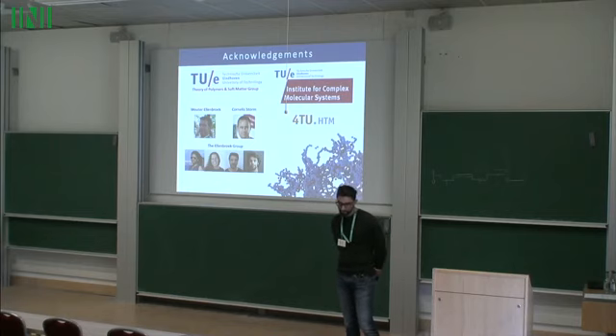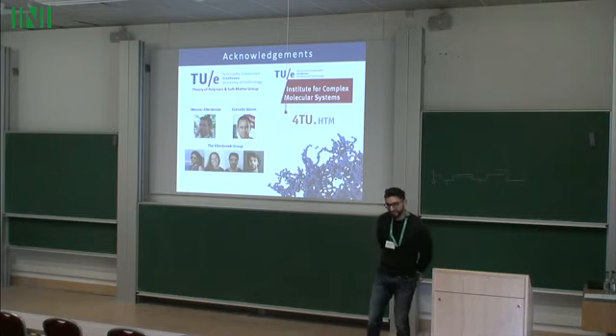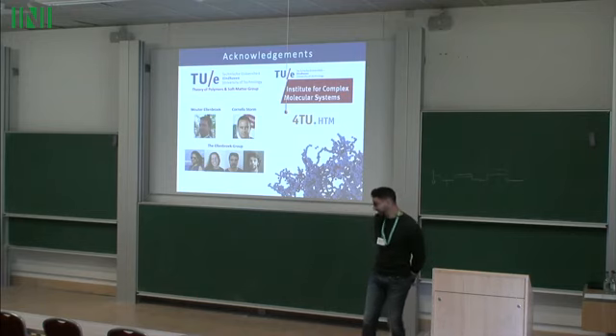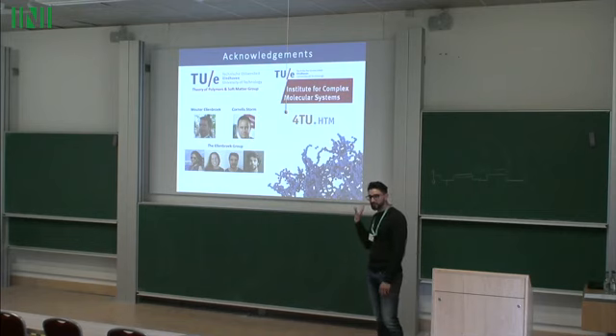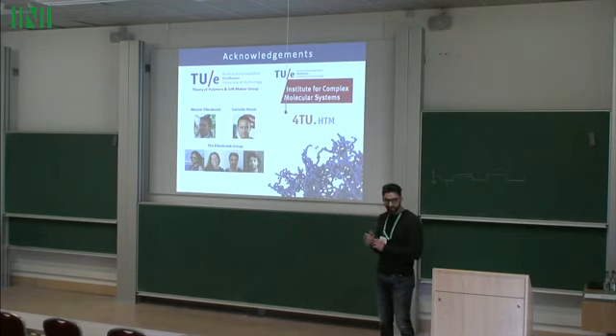What about all these composite systems that experimentalists make, which are more complicated? Can you add on to this? Yeah, I think so. This argument works really well when you have a dilute polymer network. If it's more concentrated, then it becomes difficult because you have entanglements that might govern things, and that will complicate the entropy, because now the entropy is a bit more non-trivial. So this works really well for dilute gels. But you can complicate it with different kinds of linkers. We thought about multiple linkers with multiple lifetimes, so 2 species or 3 species. It's not obvious what effect that would have yet, but you can think of those games as well.